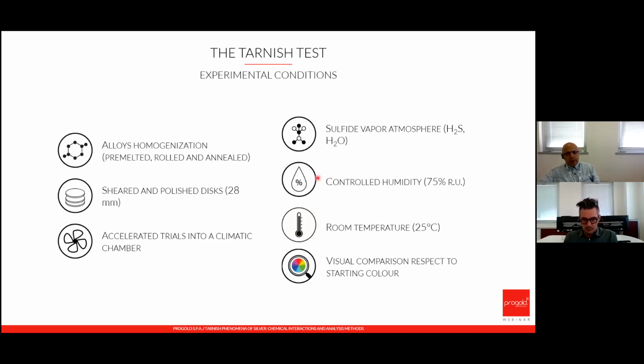This climatic box has a transparent wall in order to follow the color changes as a function of time of the metallic discs, which are hung from the chamber ceiling by means of inert wires. The tarnish resistance is evaluated by visual comparison with respect to the starting color. In other words, we were inspired by the corrosion test ISO 4538 with thioacetamide, and diluted its aggressivity.